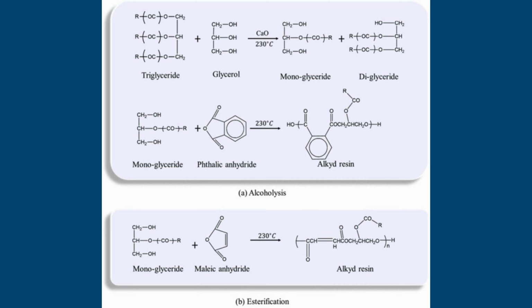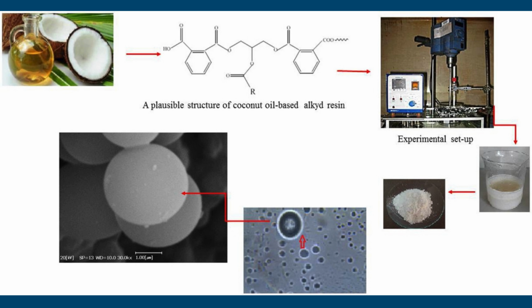Alternatively, all reactants may be combined in a single-stage process and heated to promote direct esterification. A representative preparation involves heating a mixture of phthalic anhydride, adipic acid, trimethylolethane, and neopentyl glycol to approximately 160 degrees Celsius under agitation, followed by gradual heating to around 230 degrees Celsius. Coconut fatty acids are then introduced and allowed to react at this temperature for approximately 2 hours.